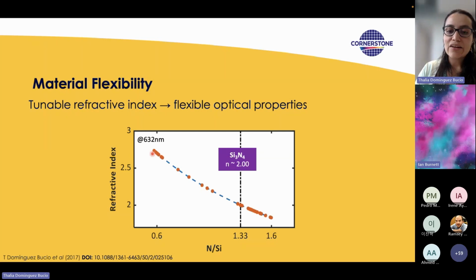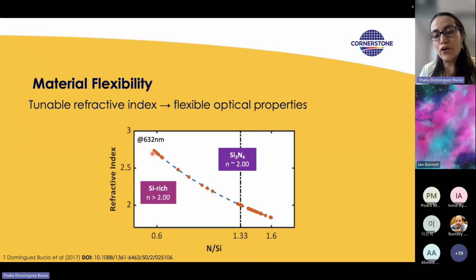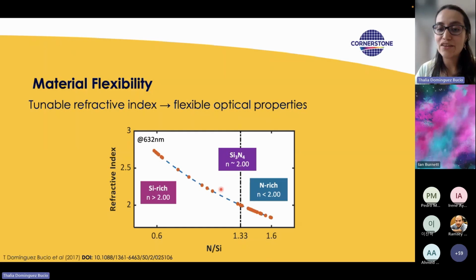Now, when we get a composition that is close to 1.33 nitrogen to silicon bonds, we get a refractive index of close to 2.0, which is the standard stoichiometric silicon nitride. If, on the contrary, we increase the silicon content of our layers, we will enter into a regime that we call silicon-rich silicon nitride. And if we deposit less silicon and increase the amount of nitrogen atoms incorporated in our layers, we will enter into the nitrogen-rich regime.